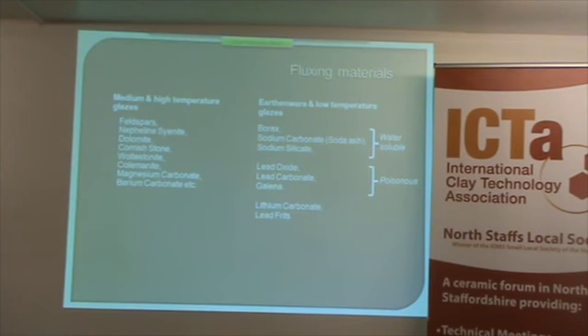So what we need to do is to make that safe. And to make it safe, we mix it with silica, usually 1 part of lead oxide to 2 parts of silica, to make the lead bisilicate frit in the same way that we do in borax frits. And so there are a range of lead frits on the market, of which the most popular by far, most usable, is lead bisilicate frit.